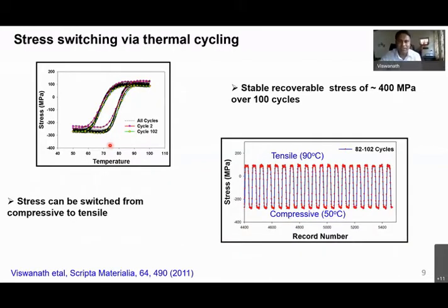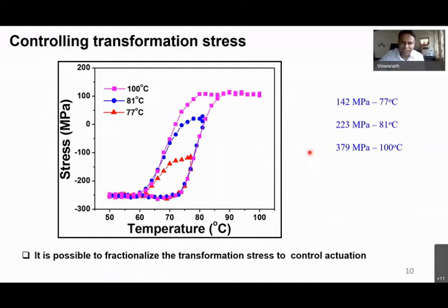Then, in fact, we tried depositing thin films and asked ourselves how many cycles we can actually switch the stress. When I say stress switching, we are able to reversibly tune from compressive stress to tensile stress. We have done around 100 cycles, which is plotted in the other plot here. I'm showing only the last 20 cycles. We can see how stress can be reversibly tuned between 50 degrees Celsius and 90 degrees Celsius. So it is extremely stable. At the same time, the transformation stress can also be controlled.